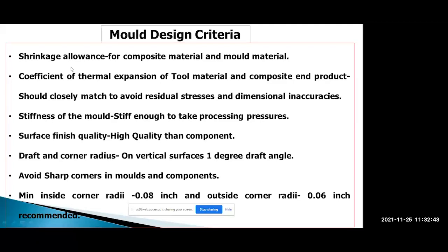The design criteria: shrinkage allowances for the composite material and the mold material, both we have to take. The coefficient of thermal expansion of the tool material and the composite end product should closely match to avoid residual stresses and dimensional inaccuracies. Sometimes, if alpha is different, mold extraction will also be very difficult. Because once it cools down, if alpha of the composite is more than the metal, then the composite will hug the mandrel. So removal of the composite from the mandrel will be very, very difficult. So we have to check these alpha values. There should not be much mismatch.